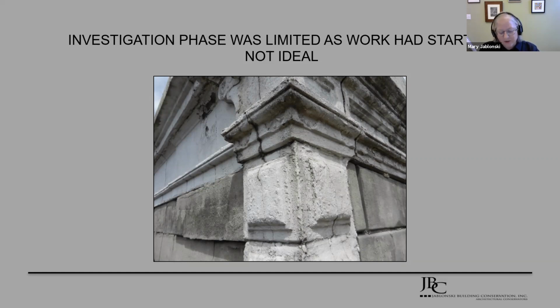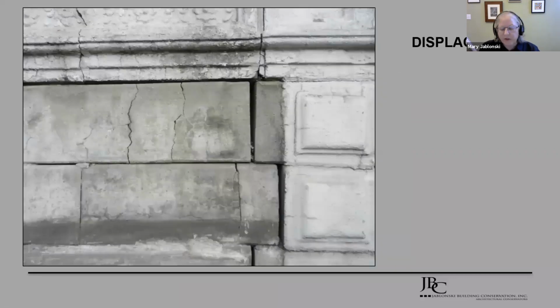Our conditions assessment started as demolition was going on around us. The displacement of some of these extremely large cast stone units, and hopefully you can see here some of these units are really quite displaced, was very disconcerting. The blocks were large and there was nowhere to run if anything went wrong. The realization of the amount of work required was a bit overwhelming, as this displacement was fairly typical for conditions on the building.